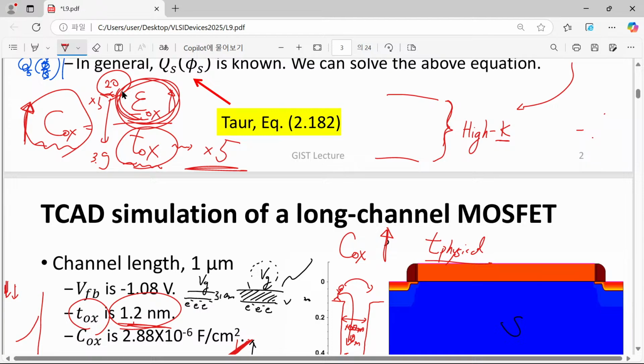The more detailed one is, here we have a silicon substrate, and a very thin layer of silicon dioxide. Usually people say that this is just one layer of silicon dioxide. On top of that we have hafnium dioxide. This is the typical high K material, and their mole fraction is like this. However, direct attachment of our high K material onto the silicon is not possible. So in order to glue them, we need at least one single layer, and this single layer is known to have a thickness of 0.5 nanometer. It is regarded as one single layer.